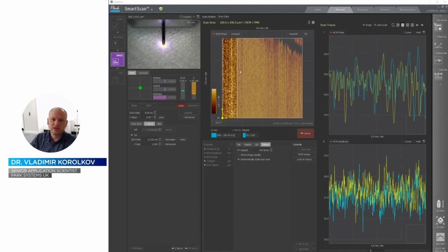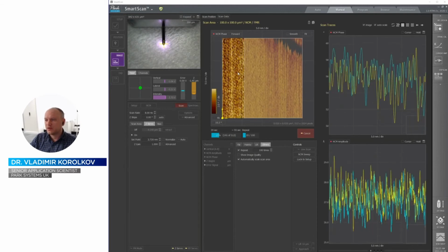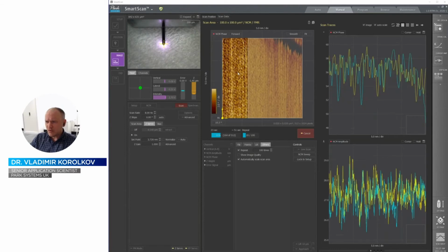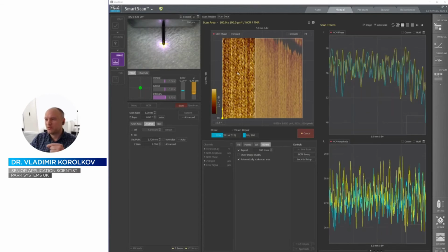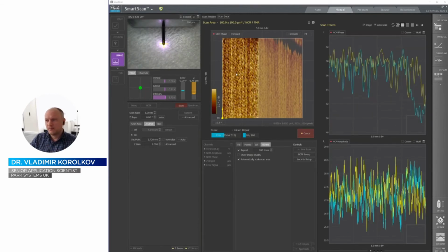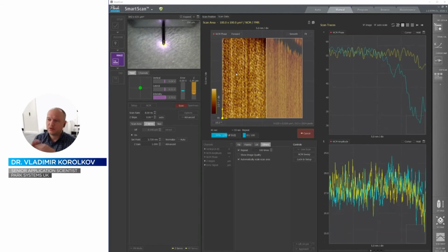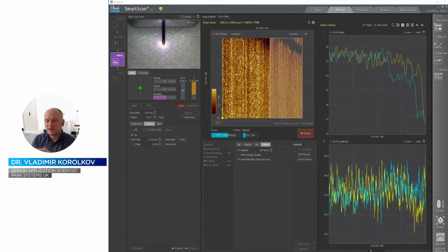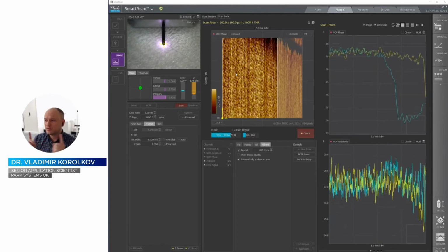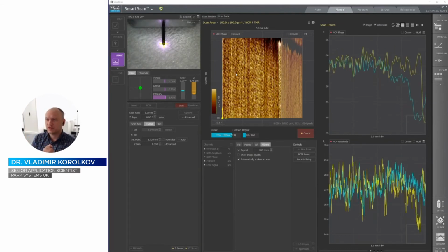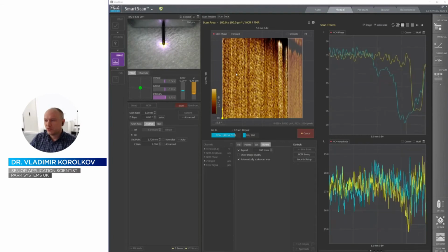Now again, the contrast is a bit better in some images, because with scanning probe techniques, the image quality slightly varies from image to image, because we're talking about extremely small length scales here. If you think about what we're saying, the distance between lines is 5.6 angstroms, but the full width at half maximum of that line, which gives you roughly the idea of the width of the molecule, is only around 2.5 angstroms or so. And to put it into perspective, a carbon bond, the distance between two carbon atoms, is 1.5 angstroms, and the width here that we are measuring is 2.5. So we are indeed measuring extremely small distances,